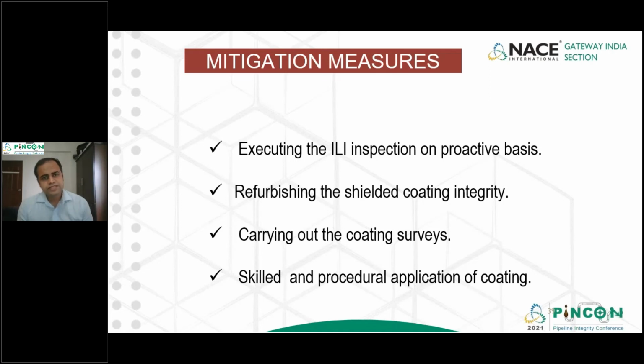Finally, how do we mitigate such issues? Well, there is no simple answer to it, but yes, I have just jotted down certain points which may be useful for the audience. First is the ILI inspection should be done on a proactive basis. Second thing is dedicated refurbishment of the shielded coating integrity areas. See, the shielded coating integrity areas cannot be solved by increasing your cathodic protection current. All that matters is you need to do periodic refurbishment of the coating integrity in the shielded areas.